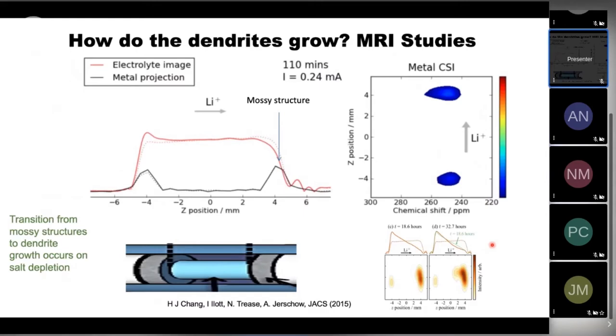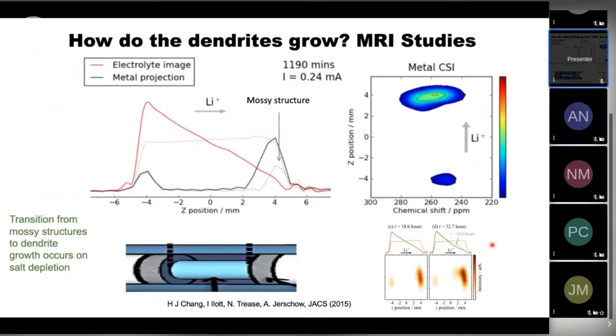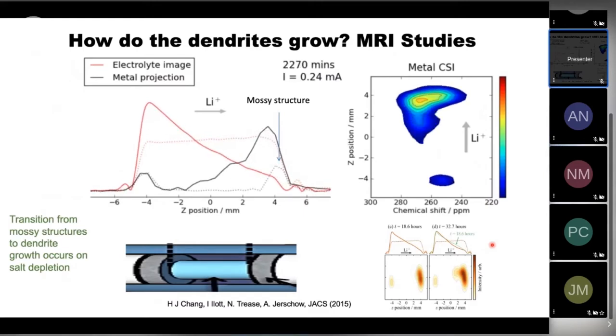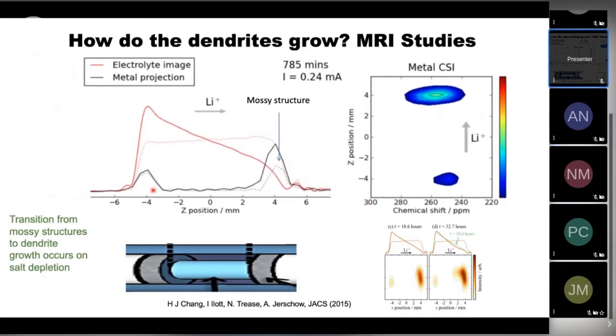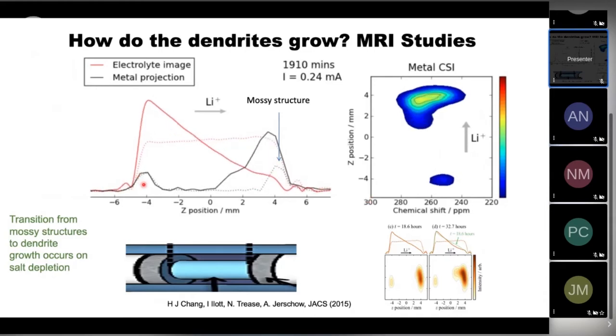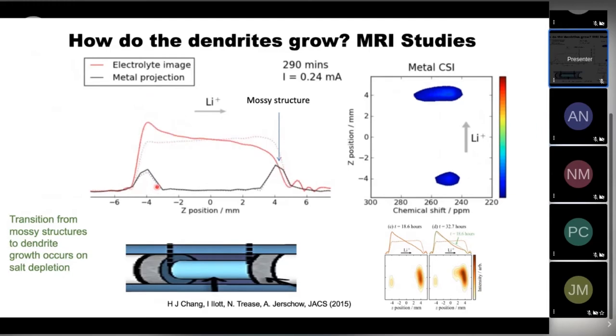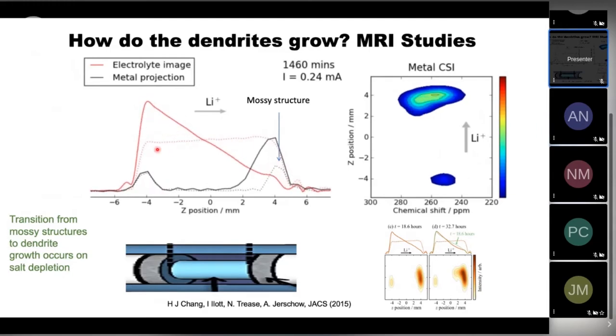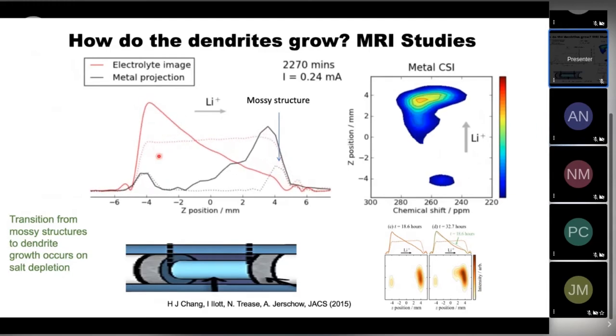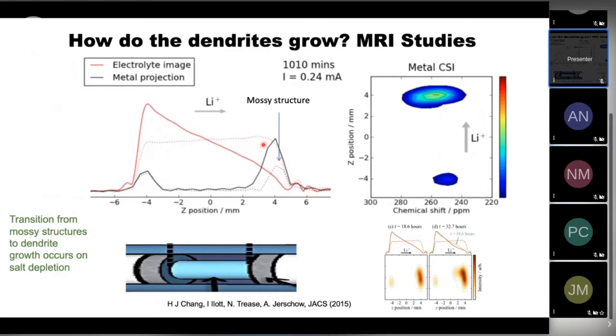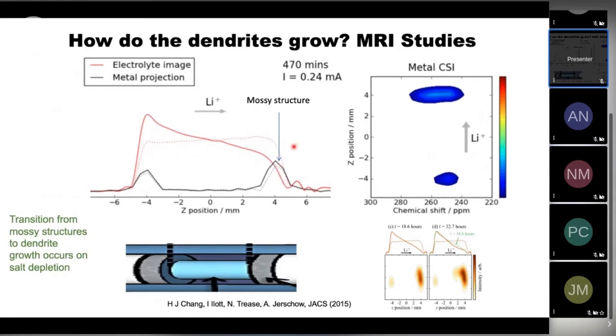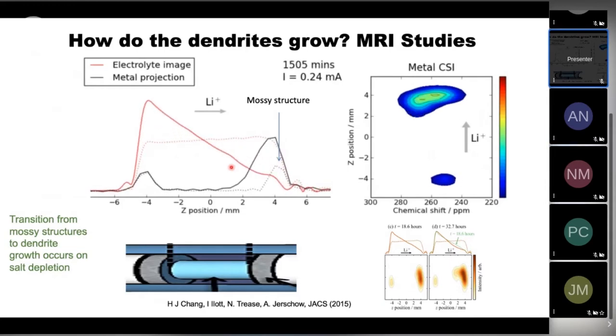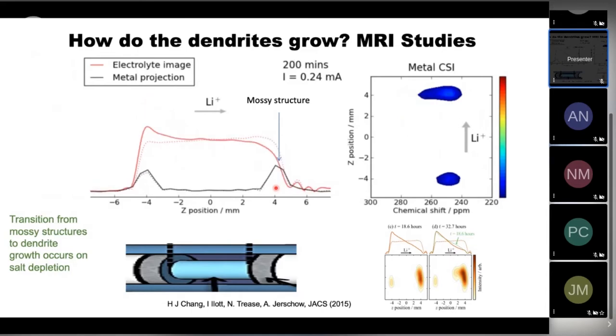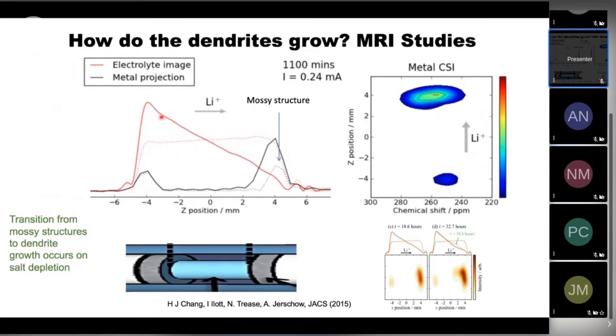So how do dendrites grow? We use magnetic resonance imaging as a method to look at this. And what you do in this case, you have lithium. We can look at both the lithium in black and the lithium electrolyte. And we're flowing current so that the lithium ions flow in this direction. The counter anions, in this case PF6 minus, flow in the opposite direction. Only the lithium can deposit and the PF6 minuses can't. And so what you see is the formation of this electrolyte concentration gradient.